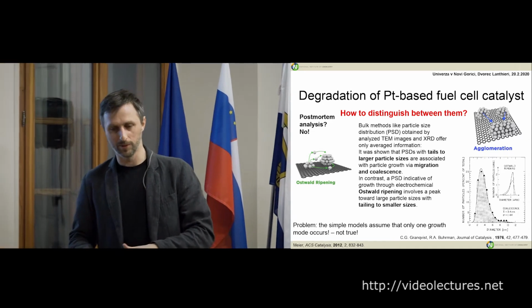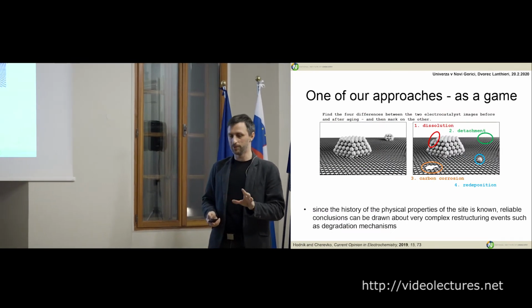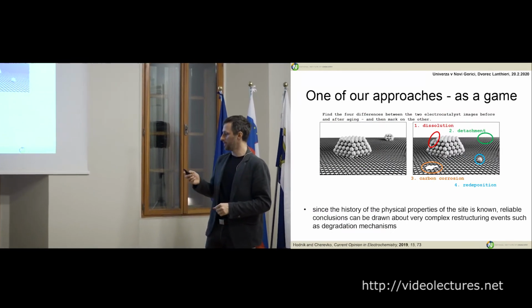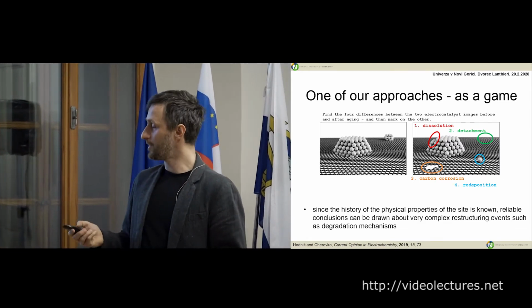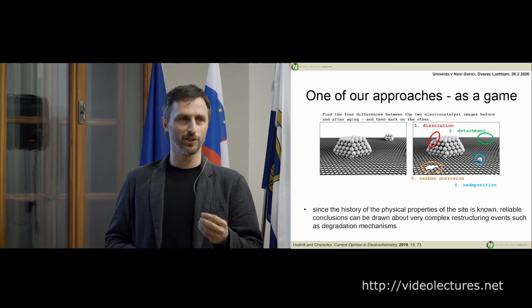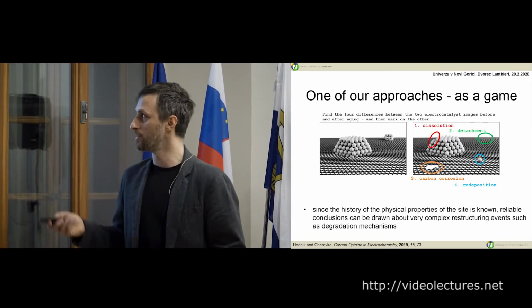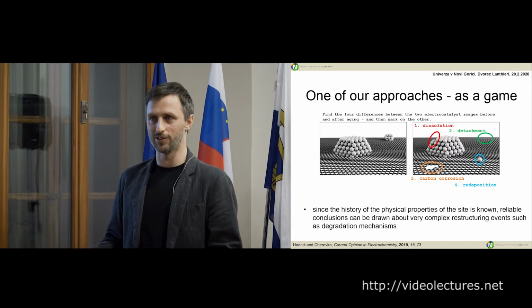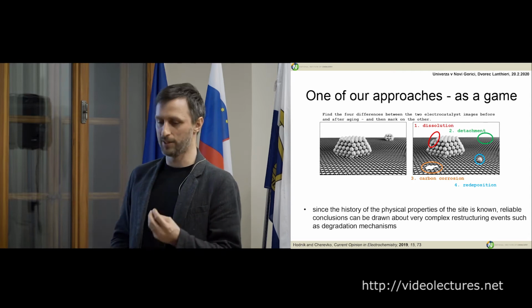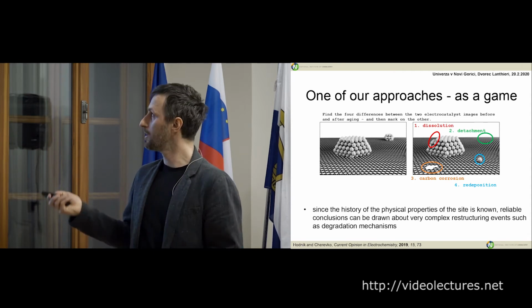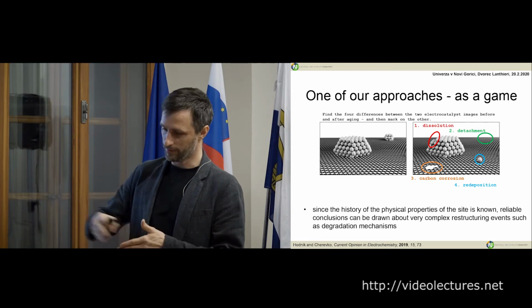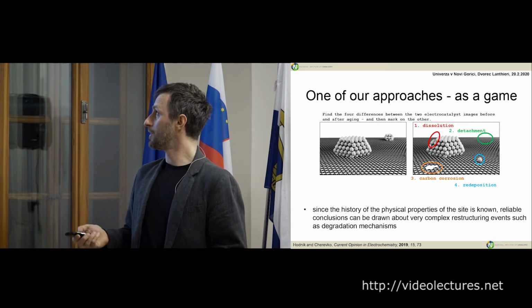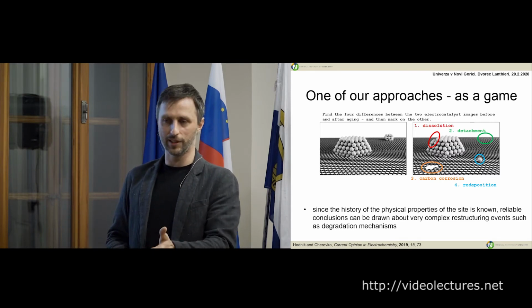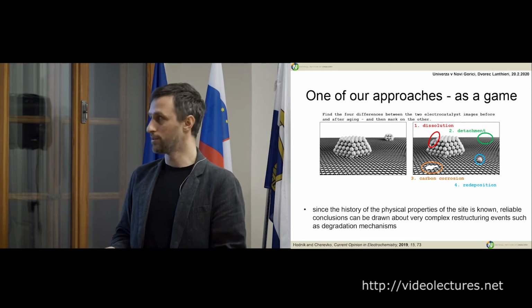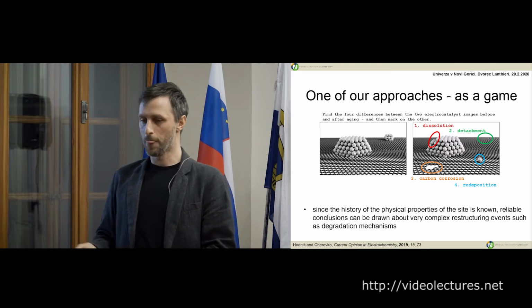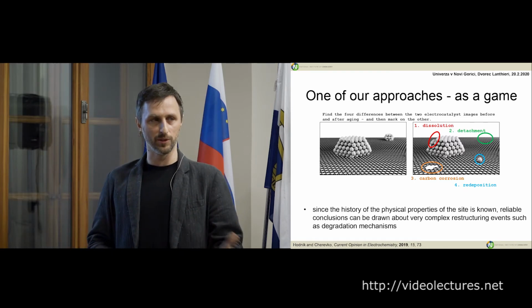Now, what I propose and what we do is we say, okay, we will care just about what happens to one particle, and we will play a game. This game is, you should find the difference in these two pictures. This picture is the same location, so it's the same picture, and you have to find differences, like in a children's game. If we map the same particle before some degradation and after, and we see there's some atom column missing, we say this must be dissolution. If there's some particle missing, we say it obviously detached or moved. If you see a hole in carbon, it's corroded, and then we see a new particle. So in this case, we are certain that this event happened because we know the history.